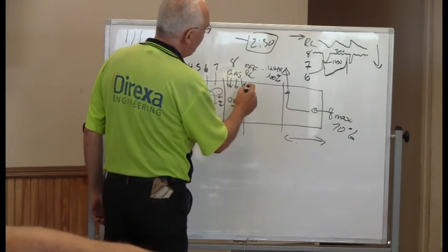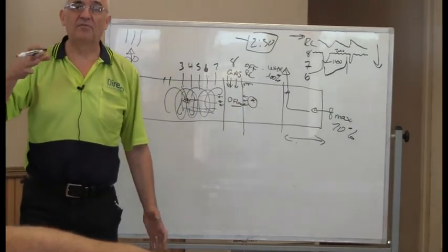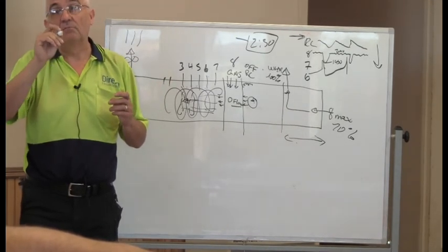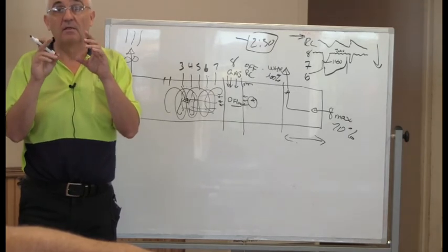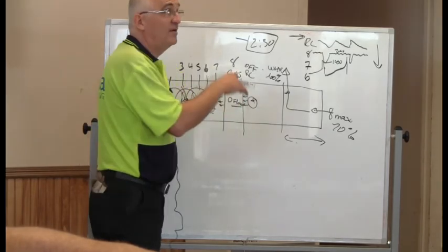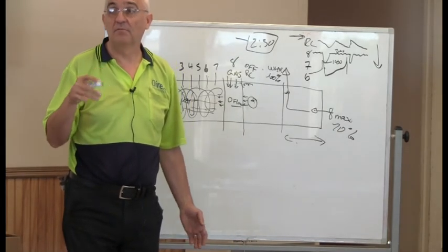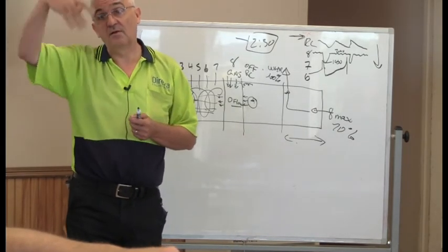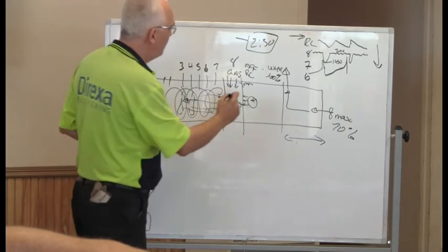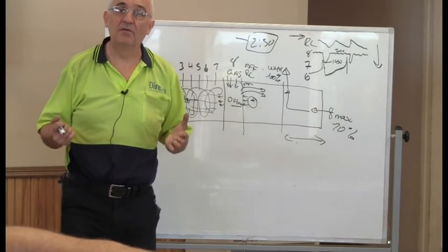I can have a bit of smoke on top of the kiln rolling backward slightly. That's just a good indication that, yeah, ideally I should have 0. You have a bit of rolling backward, okay? If I start seeing the gas here burning in the injection area, then I know I have too much. But if I see a bit of plume, what I call a plume of gas, it's okay, slightly. If you start to see the gas actually going to the HT, it's wrong.